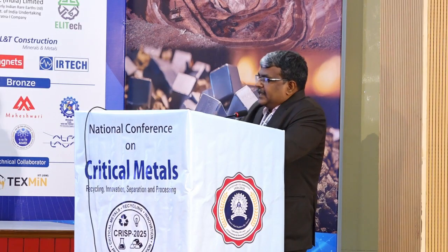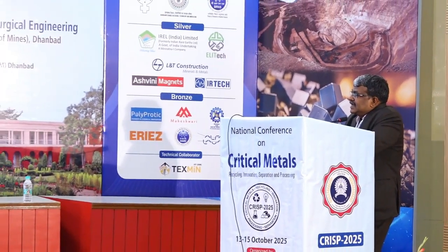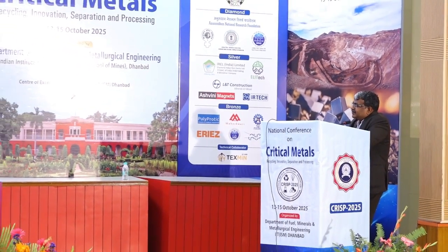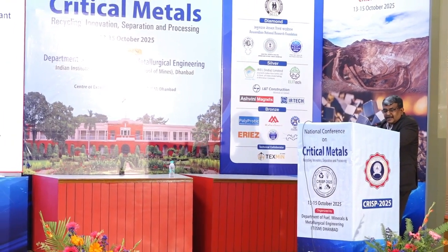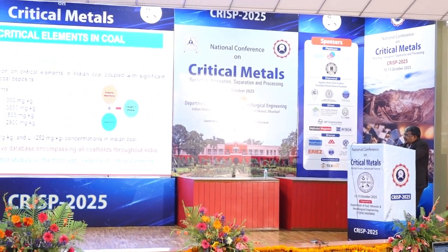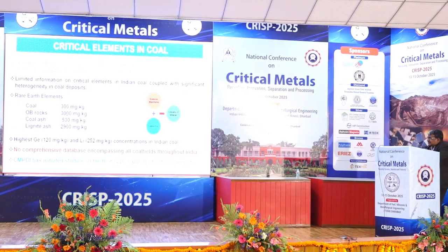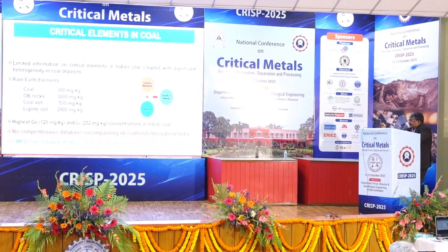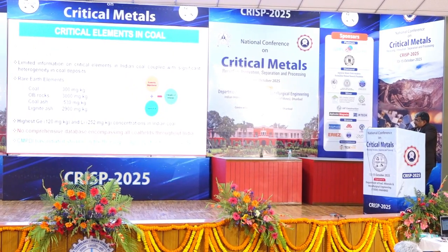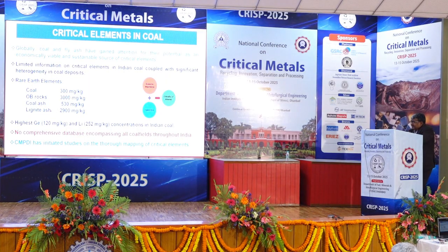Okay. So globally, recently, the US, China, and Russia identified coal and fly ash as a potential raw material for critical minerals. But in India we have limited information on the content of these critical minerals and rare earths in coal. Our data shows that the total REE concentration in coal can go up to 300 milligram per kg, ppm. Some of the waste rocks in coal mines have more than 3000 ppm of rare earth elements, and till date we have come across 500 to even less than 600 ppm of rare earth elements in coal ash. But in lignite ash, the concentration is even up to 3000 ppm at Neyveli.